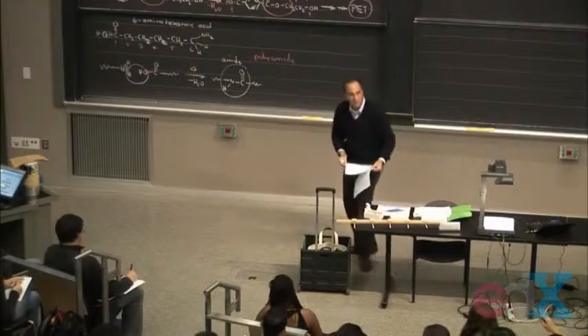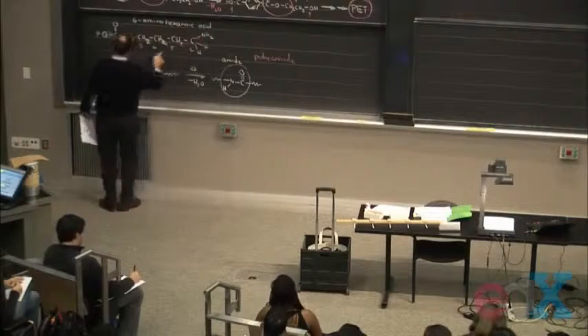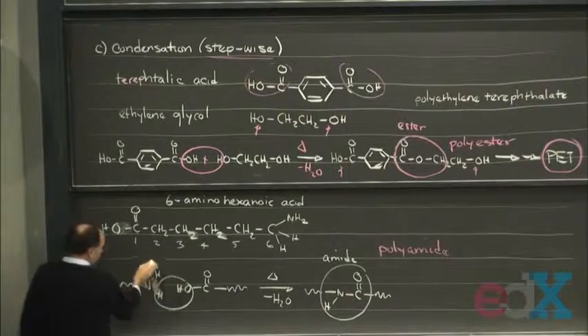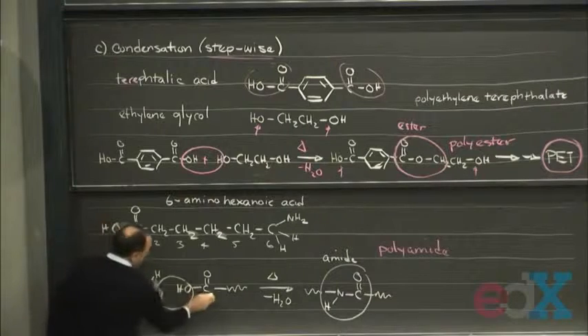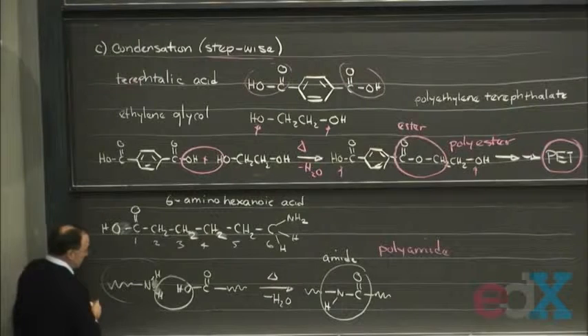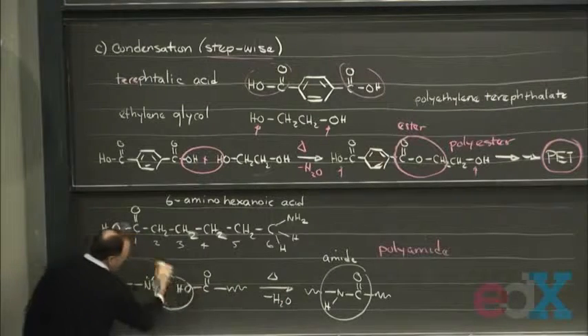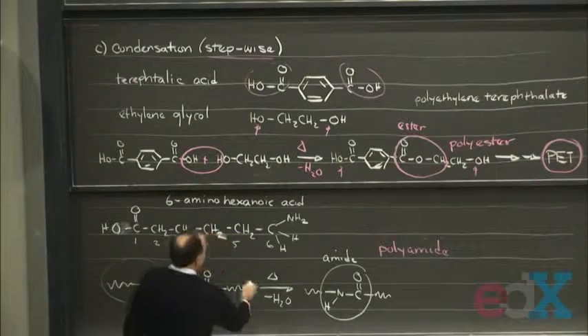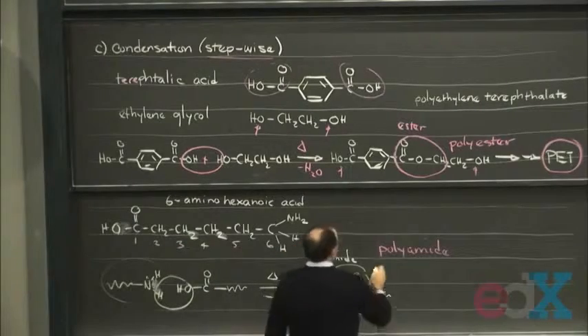So what are the reactions using polyamide again? So it's this amine group on one. So I've written it here. And the acid. So I've just drawn this end of one molecule here and this end of one molecule here. So when I heat it up, I can just have this nitrogen react with that carbon and split out the water and you end up with an amide. But it's the same basic idea. Instead of an alcohol, it's an amine. So this is nylon.